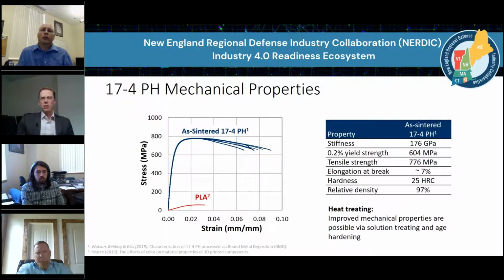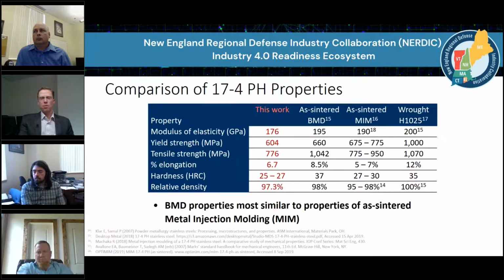As mechanical engineers, we're probably more used to these mechanical properties. So here we have stress-strain curves for the as-sintered 17-4 PH, and just for reference down here is PLA. We end up with stiffnesses, yield strengths, and tensile strengths as shown on the right. And probably even more importantly is this next slide, where we start comparing what we get with bound metal deposition versus what you see with wrought or as-sintered metal injection molding for similar materials.